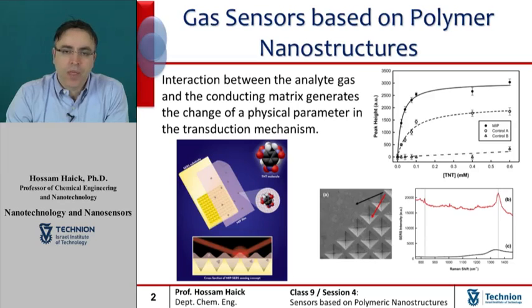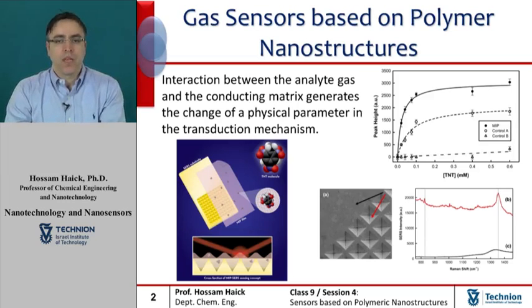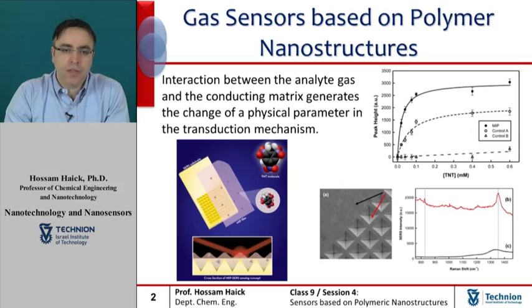As seen in the right figure, the polymer background does not prohibit TNT detection. Furthermore, the successful measurement of the TNT template within the molecularly imprinted polymers shows it is possible to develop a thin and porous molecularly imprinted polymer film which allows analyte measurement within the critical surface-enhancing field distance from the underlying substrate. The right figure shows the response profile from TNT-responsive and control xerogel films to increasing concentrations of the TNT.